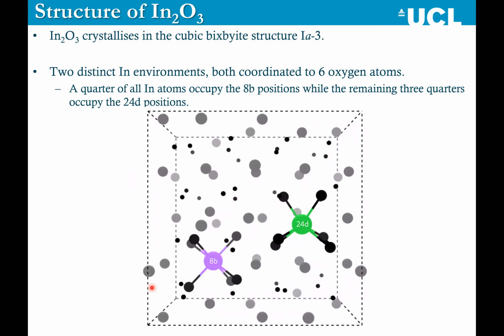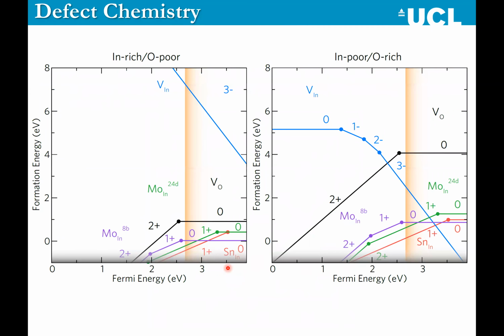So what we did to understand this was we can do calculations using the VASP code. We run these on the national supercomputer in the UK, the Archer machine, and now the Archer 2 machine. Indium oxide crystallizes in this lovely cubic bixbyite structure. It has two very different indium environments. Both are 6-coordinate, so octahedrally coordinated. But the 8b position, this purple one down here, is quite a regular octahedron, and the 24d site is a very distorted octahedral site.